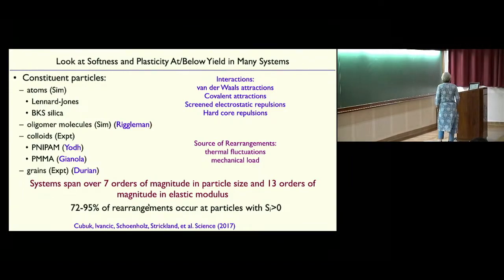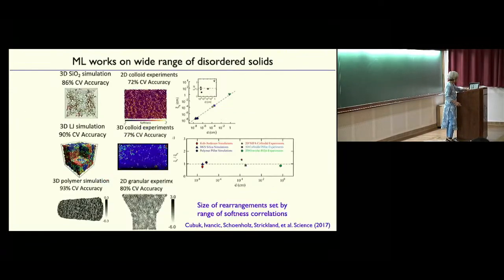The elastic modulus spans 13 orders of magnitude in these systems, but they all look the same in the sense that if you look at the correlation length of softness, it is basically set by the particle size. So it just scales with the particle size in all of these different systems. If you look at the correlation length of plasticity, it also is correlated on that same length scale. So here's the ratio of the correlation length for plasticity to the correlation length of softness as a function of the diameter of the particle. Again, this spans over 7 orders of magnitude, but you see that ratio. This is a linear scale. That ratio is very close to 1 for all of them.